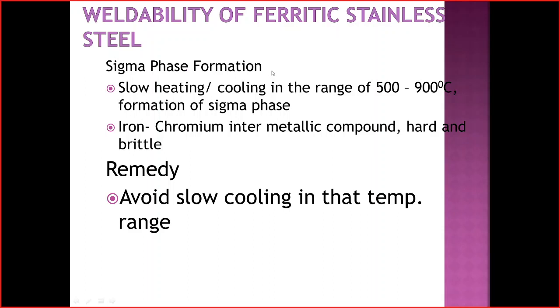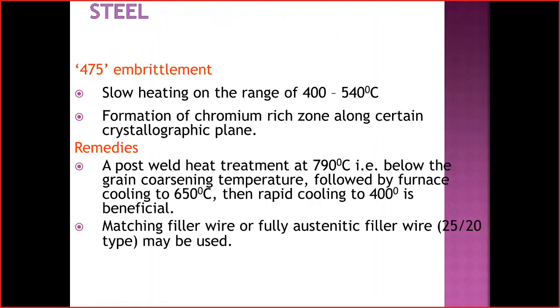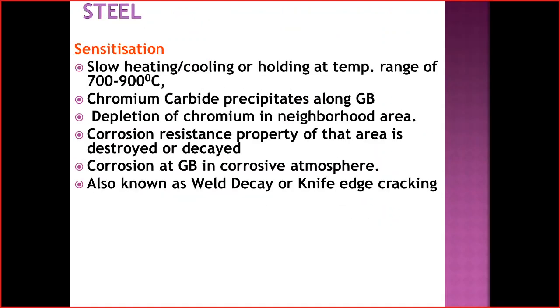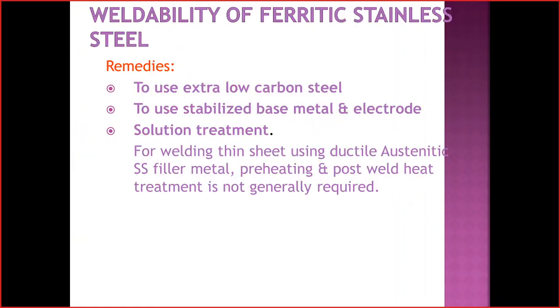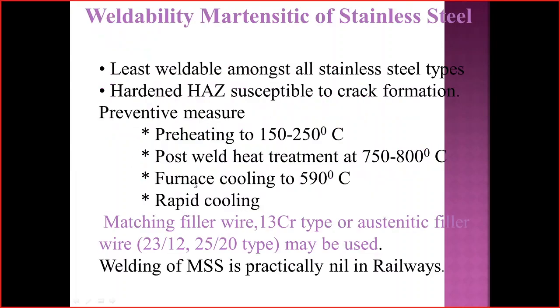Sigma phase formation can be controlled by avoiding slow heating or cooling in the range of 500 to 900 degrees centigrade. It is an iron chromium intermetallic compound, a hard phase. So you have to avoid slow cooling in that temperature range. These are the other points. This is not required. Okay, this is also not required.